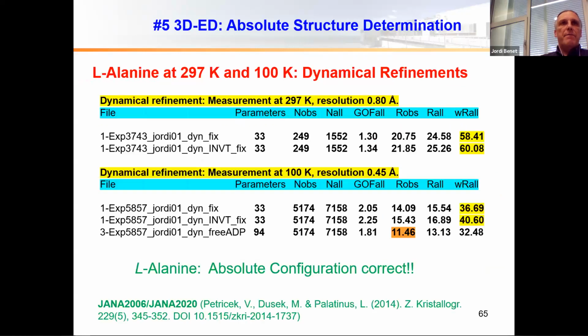And then a next step came in. We started to make dynamical refinements on both data sets at room temperature and at 100 Kelvin. And what we could see is that just refining the initial structure model in inverted configurations in the program for dynamical refinement, we could see a huge difference in the R values. So this is not a finalized structure refinement, just an initial refinement of the data set.